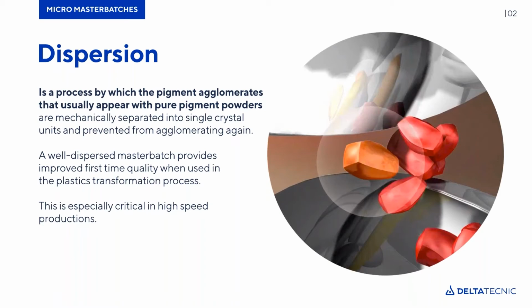It is also critical for first-time quality because pigment agglomerate inside the insulation layer of, for instance, an automotive wire, at the end of the day is an impurity. It's an impurity that may lead to sparks and therefore may reduce first-time quality. So it's not only the color strength, it's not only the positive side, it's also the negative side.